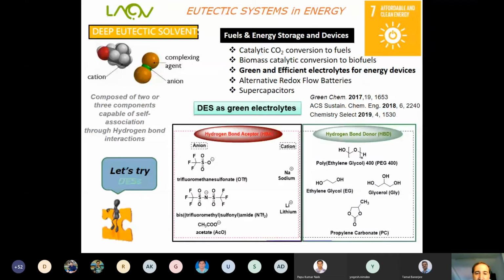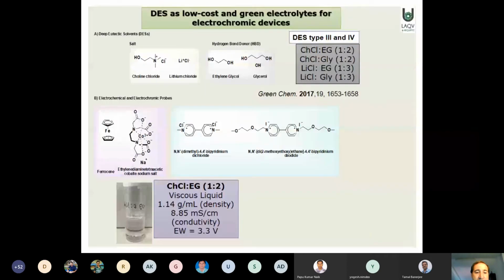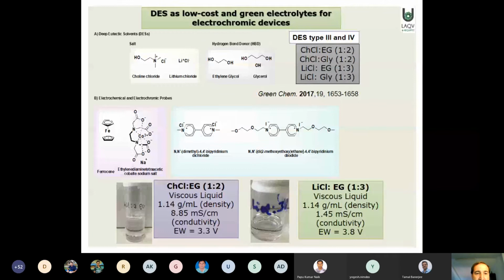And now we are using different hydrogen bond acceptors, normally sodium or lithium salts, with triflate, bis(trifluoromethylsulfonyl)amide or acetate, and hydrogen bond donors like polyethylene glycol, ethylene glycol, glycerol, or propylene carbonate. These kinds of combinations are useful as deep eutectic solvents, as green electrolytes for electrochromic devices. It means we are using different systems, low cost and green electrolytes, for electrochromic devices.